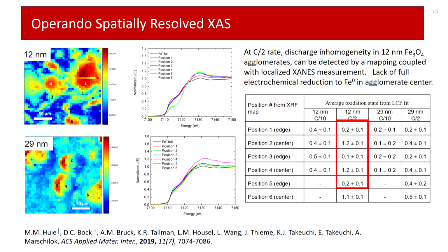We then probed the size dependence of the XAS, investigating both 12 nanometer and 29 nanometer magnetite, and mapping it using X-ray fluorescence, and then conducting a local probe of the iron oxidation state, both in the center and the periphery of the aggregates. And what we found was quite interesting.